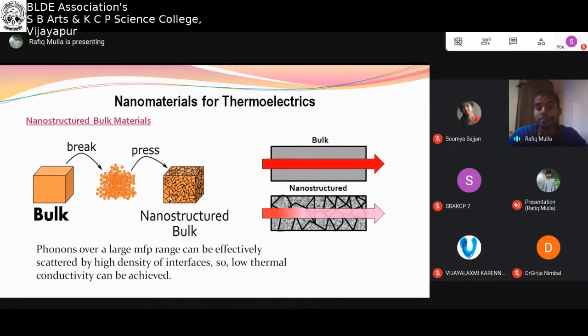In this material, we can significantly reduce the thermal conductivity. In the case of bulk material, because of the entire crystalline nature of the material, phonons can flow very easily from one side to another, or heat can flow from one side to another, because phonons are moving very smoothly without being scattered much. But in this kind of structure, we have a lot of interfaces in the material, and due to that, the phonons can be scattered at all the interfaces, and then the heat flow can be minimized. So by using this simple technique, we can suppress the flow of phonons and achieve low thermal conductivity, without much affecting the electrical properties like electrical conductivity and Seebeck coefficient.